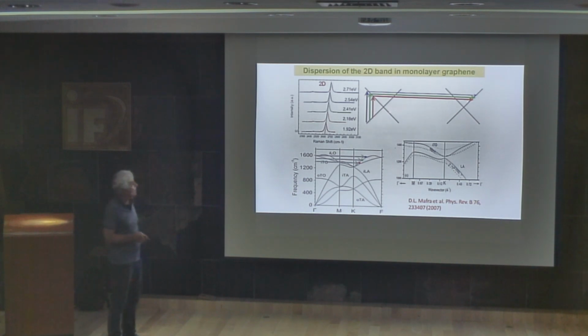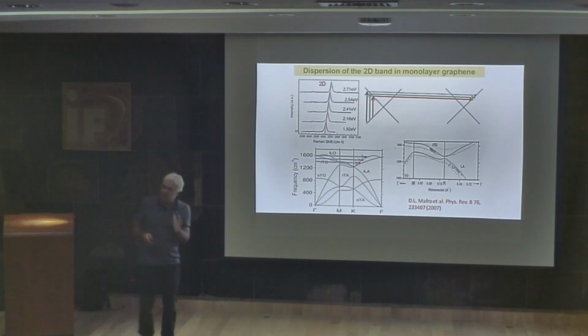And for example, what happens if I change the color of the laser? This is one monolayer graphene where I'm changing the color of the laser. This is the red laser, yellow, green, blue. And you can see that now the position of the peak changes when I change the laser. But one thing that I would like to say is that the Raman shift is the difference between the Raman peak and the peak of the laser. Then, since it is a shift, normally the position of the peak in the Raman spectrum does not change when I change the laser, because it's only a difference.